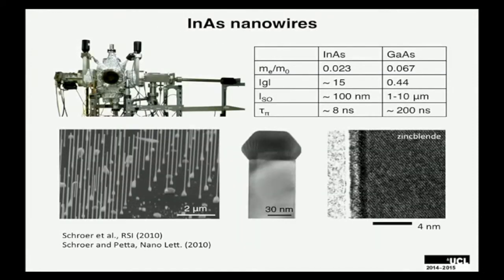The indium arsenide nanowires we use at Princeton were grown using a home-built UHV-MOCVD reactor, and in Copenhagen the wires are grown using MBE. In both cases you can produce very high quality single-crystal indium arsenide nanowires. Comparing InAs nanowires with GaAs: you have a very low effective mass enabling strong spatial confinement, a very large g-factor allowing you to work at much lower magnetic fields, and a very short spin-orbit length meaning strong spin-orbit coupling enabling fast spin rotations using electric fields on nanosecond timescales.